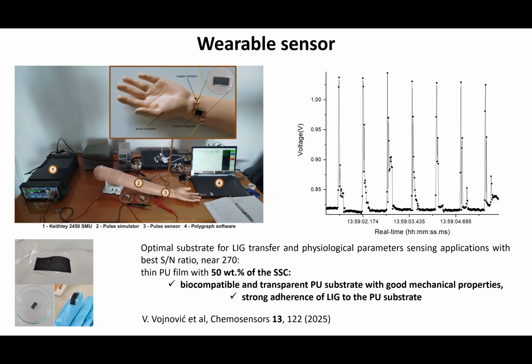You can set the same intensity, for example, and see which sensor performs better. And this one performs very well. You see on the right, this heartbeat is registered very, very clearly. Signal to noise ratio is high. As we measured, it's 270. And we found that the optimal soft segment content for this is 50%. You can see all about this in the papers that I keep citing at the bottom of my slides.